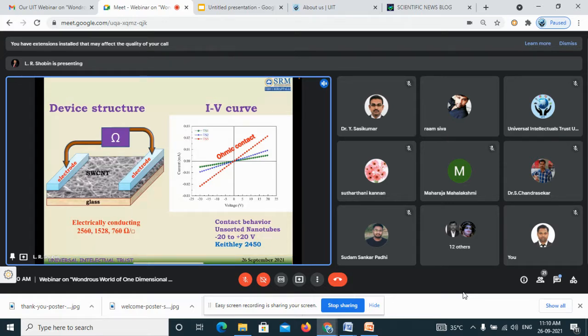Transparency is achieved. Let me check the electrical properties. So in order to test it, I fabricated a silver electrode on it. I want to test whether this electrode has an ohmic or Schottky contact. If it is an ohmic contact, whatever the resistance I measured is from the films, I can assure that there is no resistance variance between this electrode and the fabricated film. So I tested that device in IV curve. It's linear in nature. So it shows that these contact electrodes are ohmic in nature and their resistance is like 760 ohm per square.